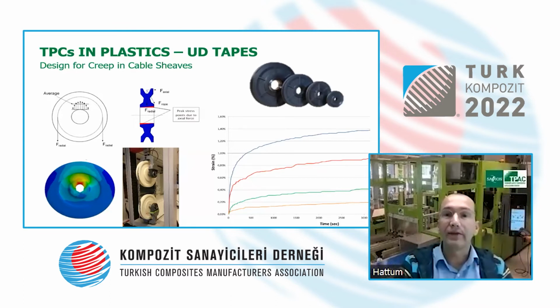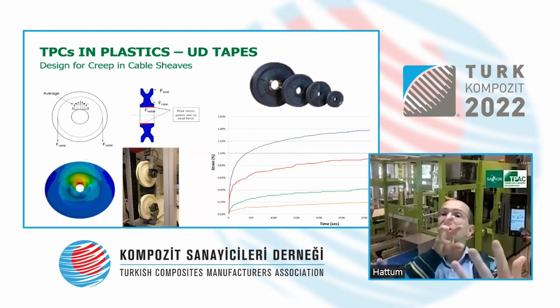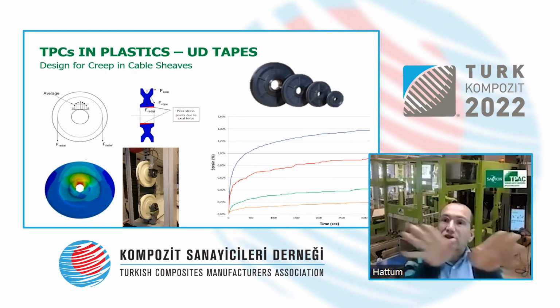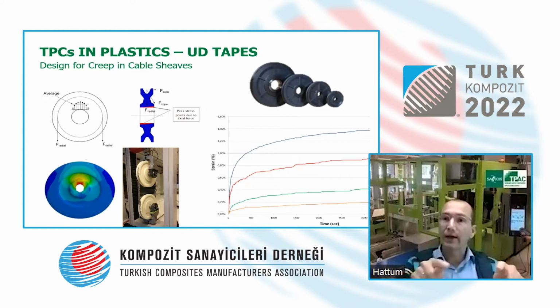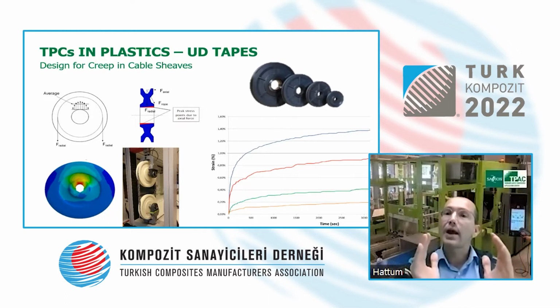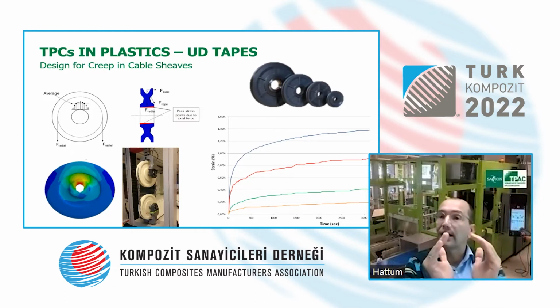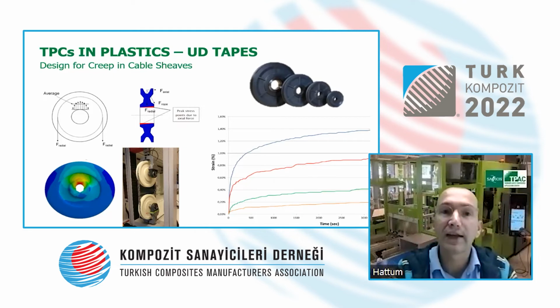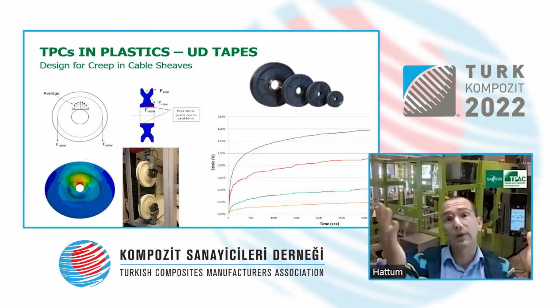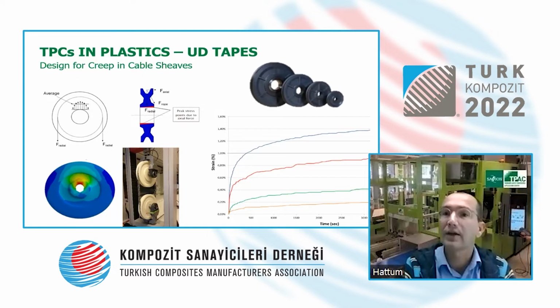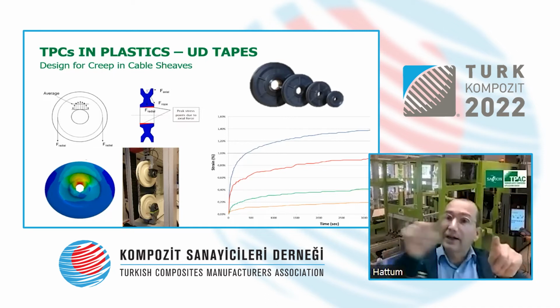What we then defined, we made a flower-looking kind of insert, integrated that into this application. Through the fibers, the force is distributed over a larger area, so locally the stresses became lower, and as you can see at the top right-hand side, where before they could only use this kind of technology, a piece of plastic versus the steel alternative for the smaller dimensions, they could gain a little bit versus the steel alternative, saving a factor of 4 over the weight, because, well, let's face it, steel is good stuff, but it's really heavy, and replacing it by reinforced nylon. But this has only been possible by integrating a 3D printed flowery insert.